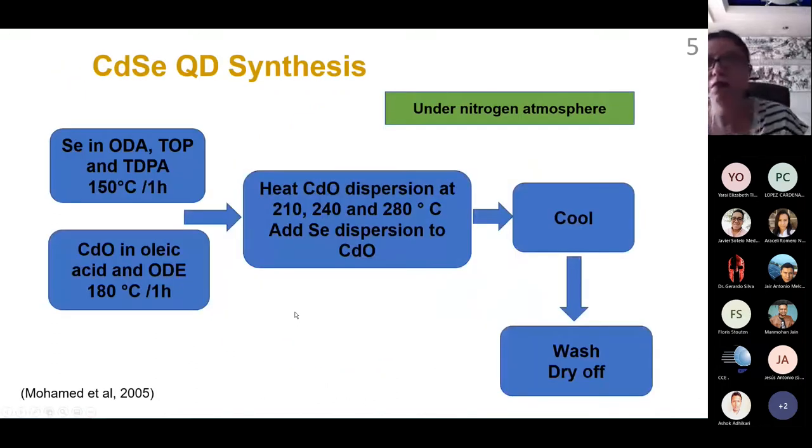Okay, the quantum dots synthesis is carried out in a nitrogen atmosphere. We need two precursors. One precursor is for selenium. We use selenium powder, dispersed in octadecylamine, trioctylphosphine, and tetradecylphosphonic acid. This is stirred for 1 hour at 150 Celsius degrees. And the other precursor is for cadmium: cadmium oxide, oleic acid, and octadecene, stirred for 1 hour at